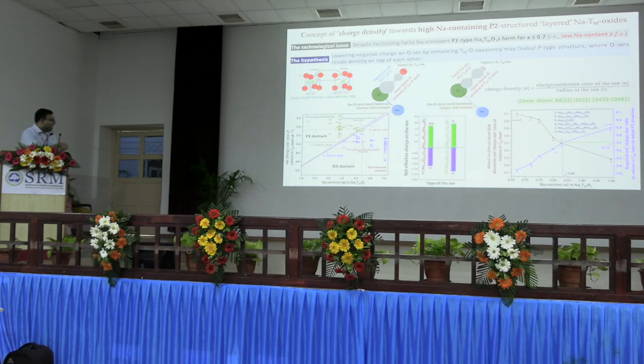Now for P2 structured layer transition metal oxide, why this is important is, if we look at the coordination, octahedral versus prismatic, in octahedral coordination the oxygen ions are not directly one on top of the other. They are slightly tilted, whereas in the prismatic coordination the oxygen ions are right on top of the other. So for prismatic coordination to be stable, we need the effective negative charge on the oxygen ion to be less negative, so that they are okay staying one on top of the other. And how do we do that? Again, going back to the concept of covalency of my transition metal oxygen slab. If I have a greater covalency of my transition metal oxygen slab, I will lower the effective negative charge on my oxygen ion, and I will allow them to stably stay directly one on top of the other and form a stable configuration.